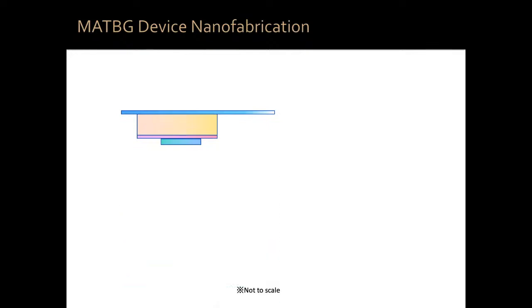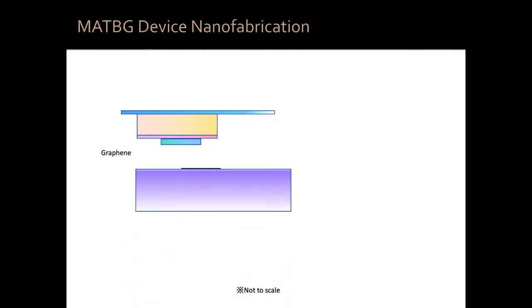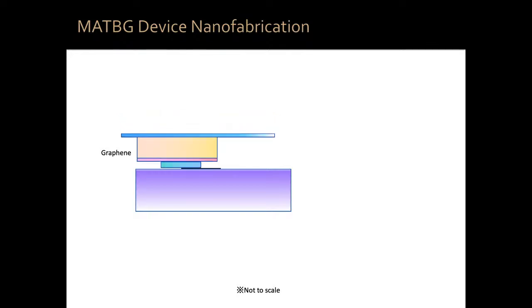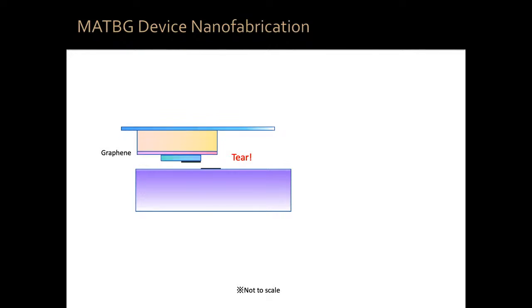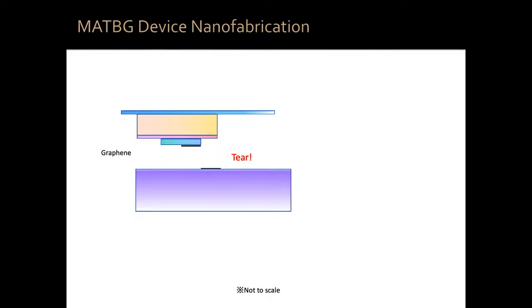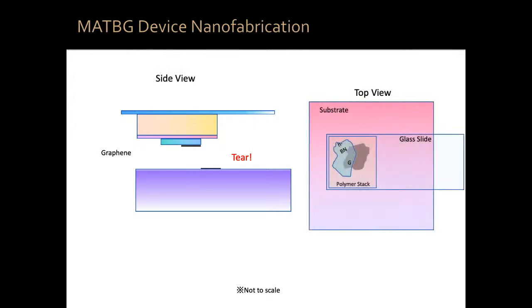Then we bring another substrate which has a monolayer graphene sheet, a one-atom thick graphene sheet. That's something thousands of groups around the world can do. It's no problem at all. And what we do is we position our hexagonal boron nitride halfway on top of this graphene sheet. We now tear half of the graphene sheet. But of course, both halves come from the same original graphene sheet. So from the top, we have the substrate, the glass slide with the polymer, the hexagonal boron nitride, and half of the graphene there, and the other half here. But they are aligned crystallographically with respect to each other.